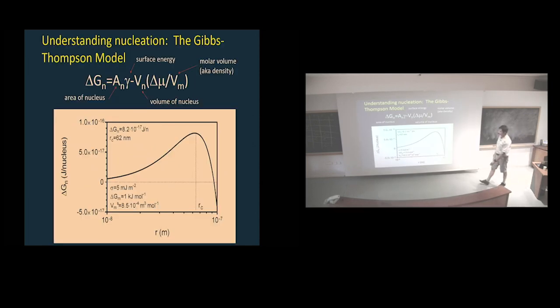Nucleation, at least the way it's understood, classic view, you have a melt, you form a ball, it's supposed to be spherical, which again, I'll show you evidence that the ball thing is not too wrong. I'll show you more about this. And then what happens when you form a ball of these triglycerides, you form a surface interface between the solid and the liquid with a minimal interfacial tension, but a measurable interfacial tension. I always found that really weird, that a liquid and a solid triglyceride would actually have an interfacial tension in between them. Whatever. So you create a surface with an interfacial tension.